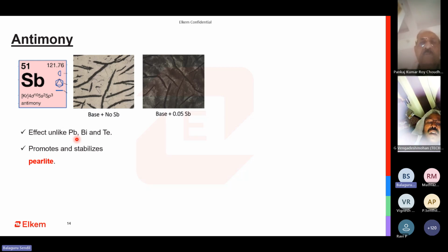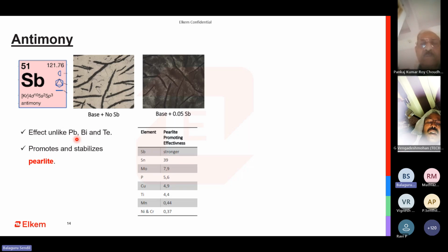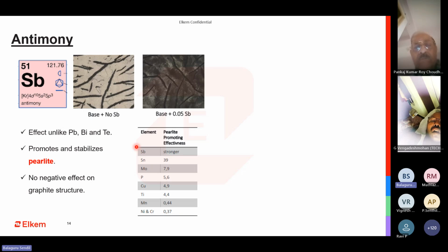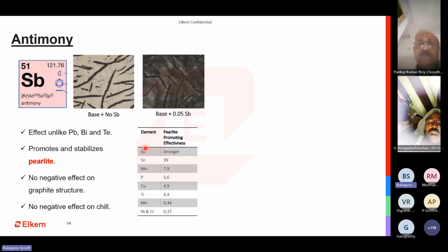So if you want to achieve a pearlitic material, just add antimony for gray iron. Pearlite, as I told, it is the strongest promoter of pearlite. Even at extremely low addition percentage, you will end up with getting pearlite. So this is the advantage of it. The disadvantage is that if you are not able to control how much it is coming, where it is coming from, then you might end up getting higher amounts of pearlite, which can cause problems.